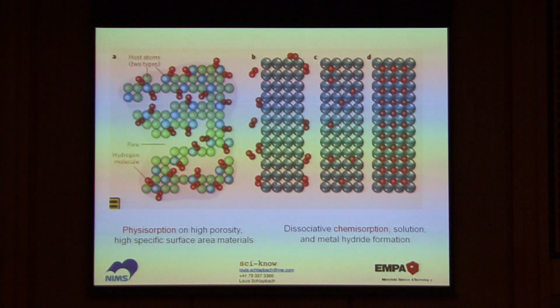In simple words, the two possibilities are physisorption of molecular hydrogen on high porosity, high specific surface area materials—and today no materials are known which do that reversibly around room temperature, so cooling is needed. The other way is chemisorption: dissociation of hydrogen molecules at the surface by specific catalytic processes, and dissolution into metal hydride or solid hydride formation, ordered or disordered, where the enthalpy of that solution or hydride formation, with a lot of thermodynamics behind it, dictates at which temperatures the process is reversible.